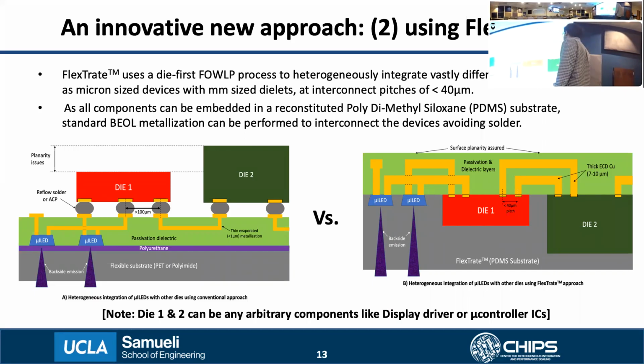Yeah, so you're right. That would be a disadvantage here because the light has to first pass through the PDMS before coming out. But we can typically thin the dies to maybe around 50 microns, or less than 100 microns. So the PDMS is a very low loss material for most of the light wavelengths that we talk about here. So the light would not attenuate that much when it comes out through the PDMS.